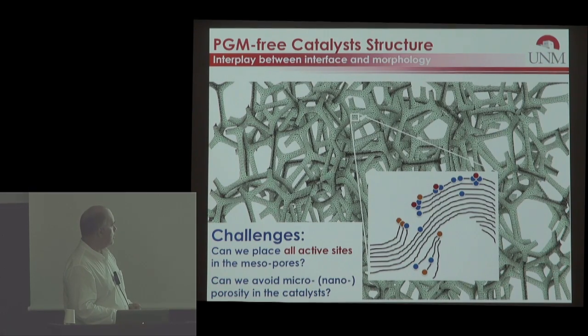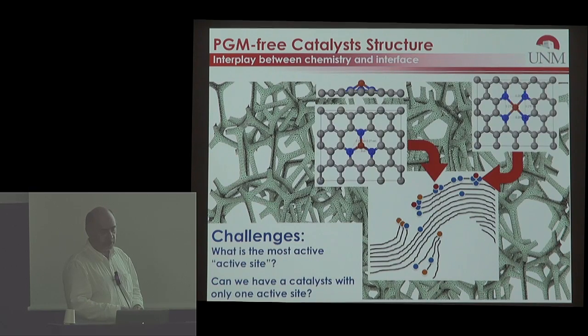So we still don't know where the most active sites are placed, whether in the pores, or in the defects, the cracks or crevices, or in the planes. Because we have observed materials in which in-sheet order dominates and you have a high catalytic activity, and we also observe materials that are highly turbostratic and also have a high catalytic activity. The only thing we know anecdotally is that highly turbostratic or amorphous carbonaceous materials are more prone to corrosion and lose activity faster. That's the only thing we can infer at this moment. This is our level of knowledge, or lack thereof.